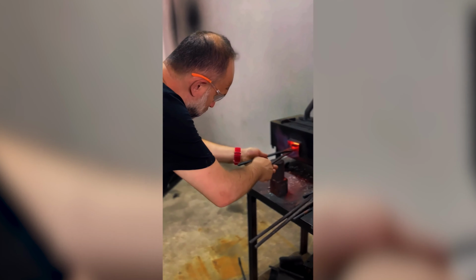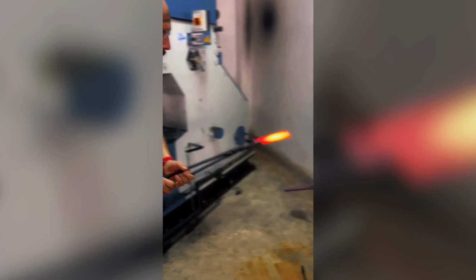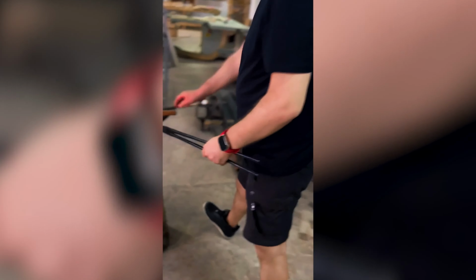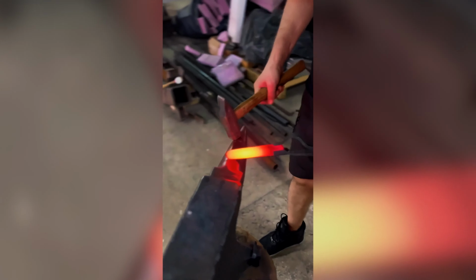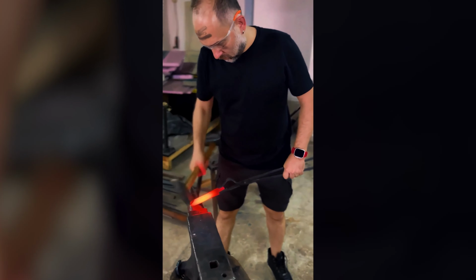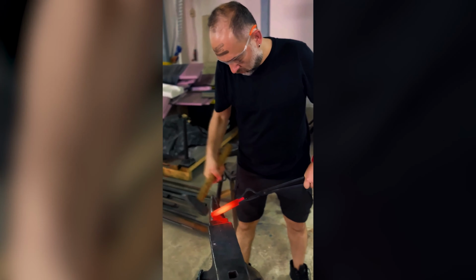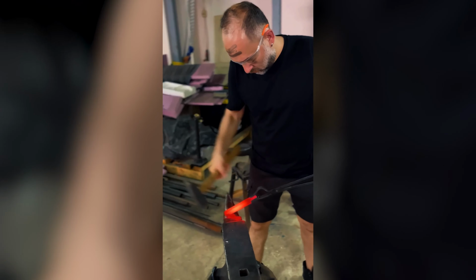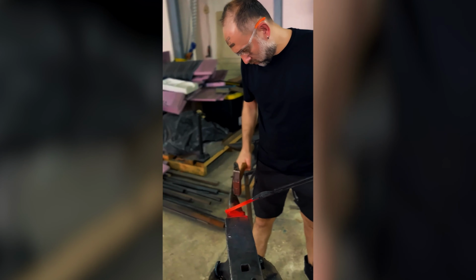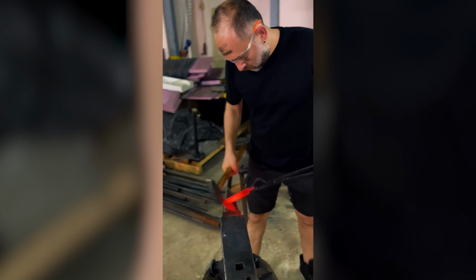Steel slowly heats in the forge. The master does not keep the material in the hottest core of the flame. The steel is constantly moved within the peripheral heat zone of the forge. The reason for this is to prevent surface decarburization and excessive oxidation.